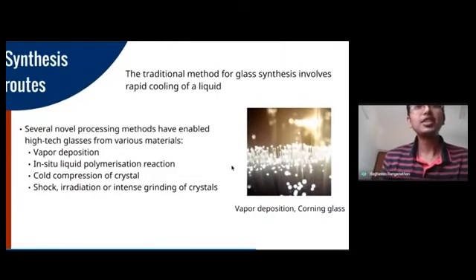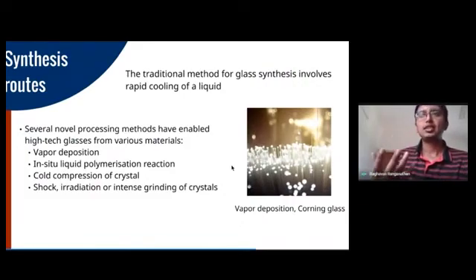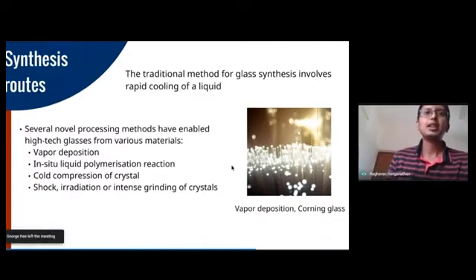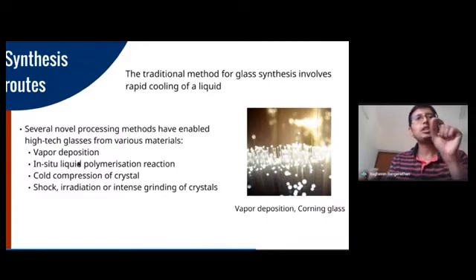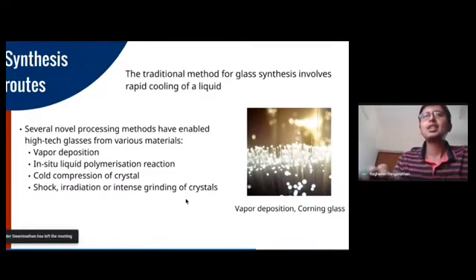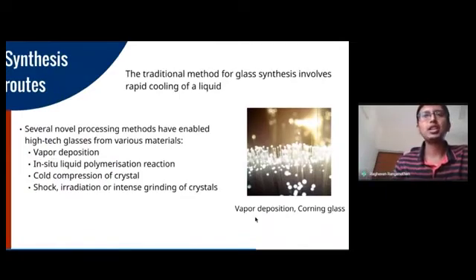And there are several other synthesis routes that I wanted to briefly mention. The traditional method that we know is rapidly cooling a liquid, but there are several other possible technologies that we can use for getting these high-tech glasses. What's very interesting is you can deposit a small set of vapor of this liquid on a substrate, and this is called vapor deposition. And this was used very successfully by Corning and several other companies for creating glasses with superior strength that were used in optical fibers, in cellular devices, and so on. Some of these other techniques are also listed here. Just skip them for want of time.